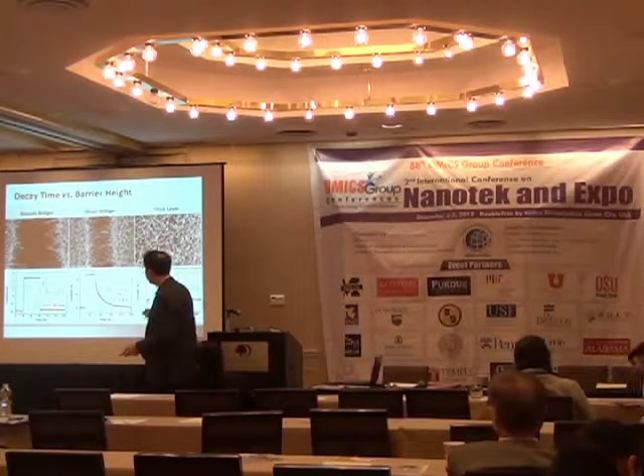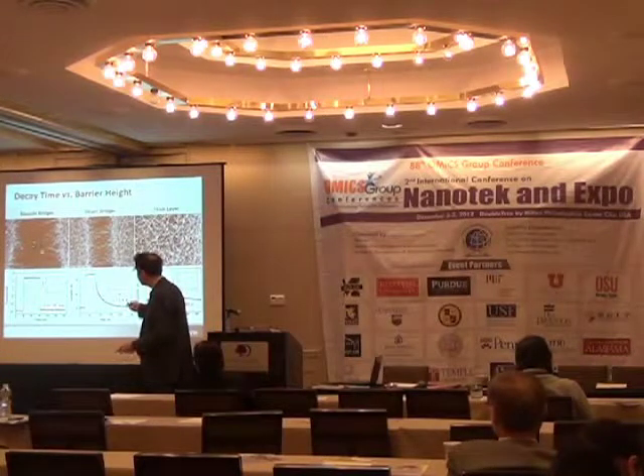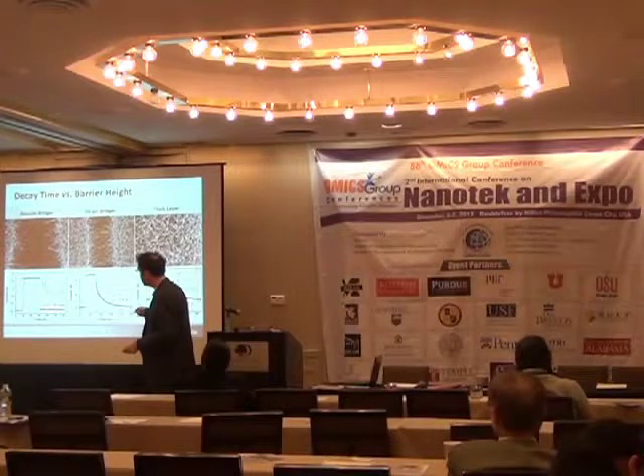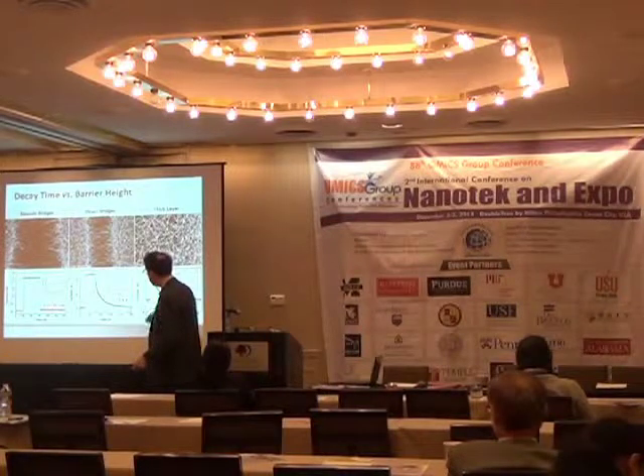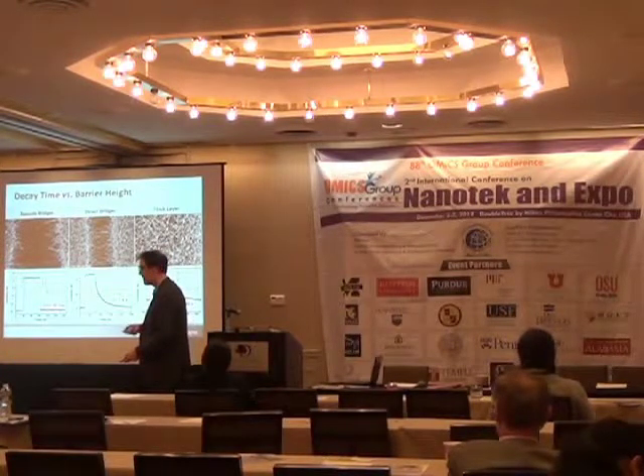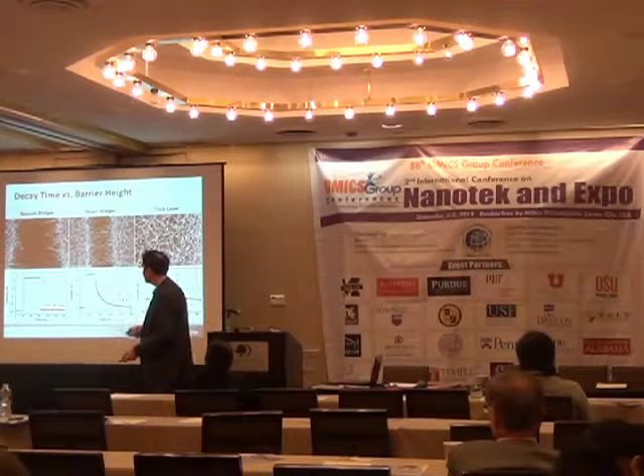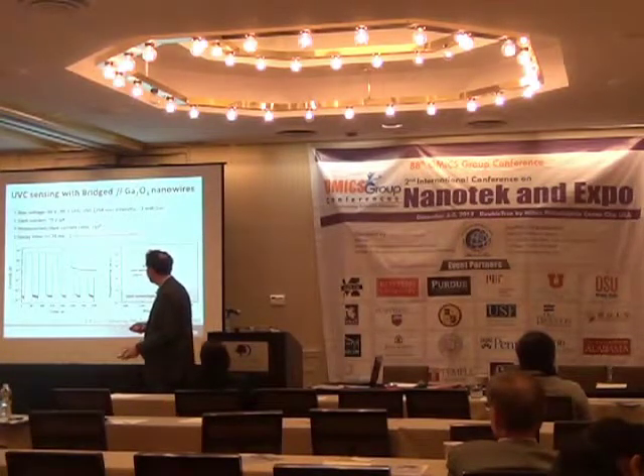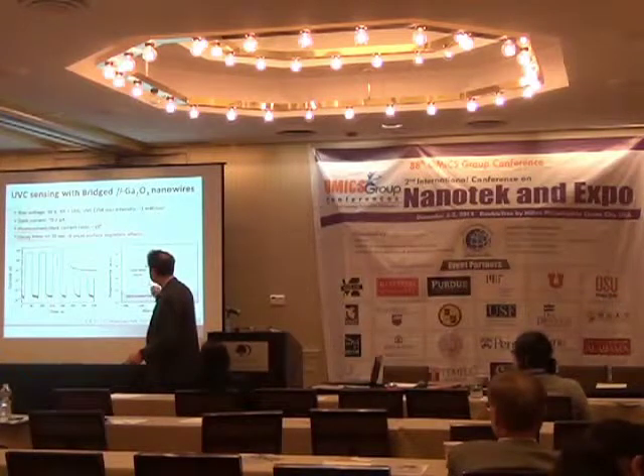Good. Okay, so we can make different kinds of bridges. We can form a junction in the middle of the gap that gives you a double Schottky barrier like IV curve like this, and a very fast response of the current, or a direct bridge that is almost ohmic and has a kind of interesting response, or very thick layers that are not very interesting. So this is the way we control the response between different kinds of bridges. Okay, so the final story of that with the bridge structure is that we have done that with gallium oxide, and now we do this.